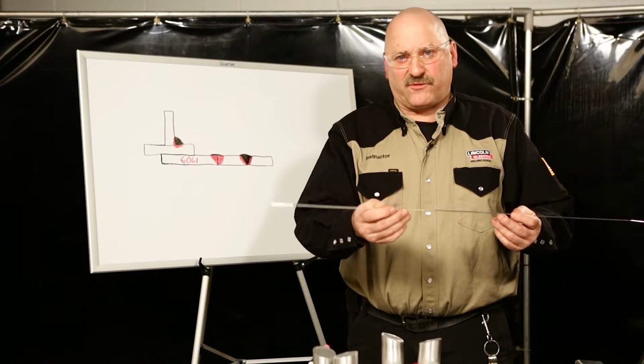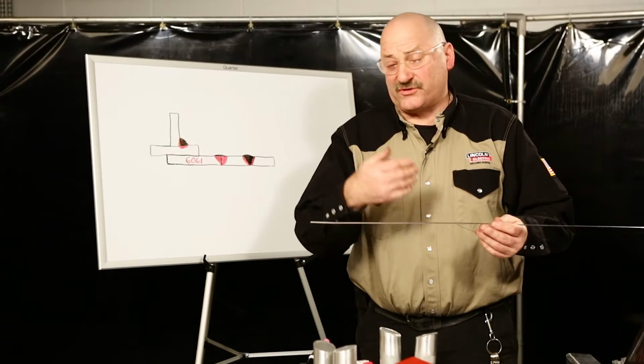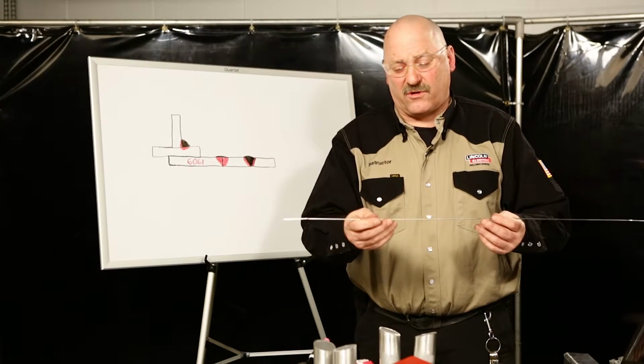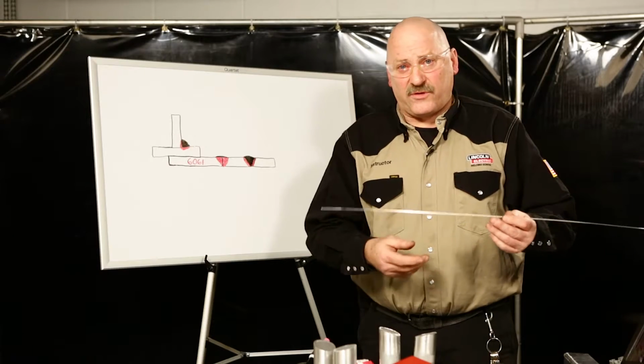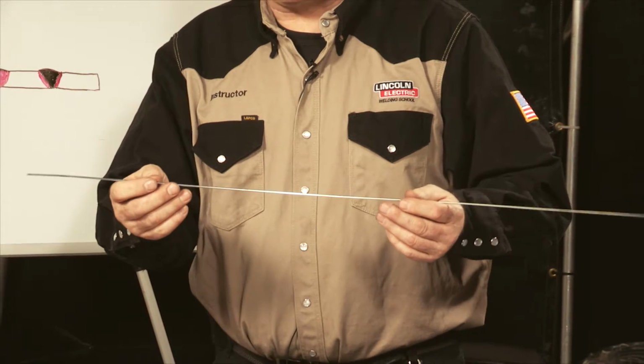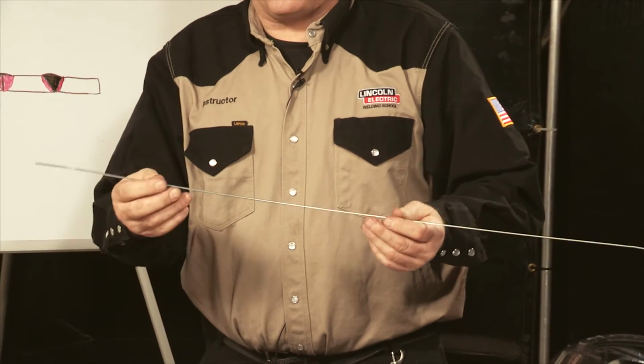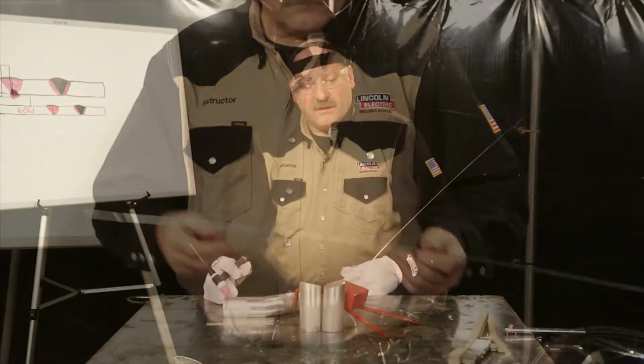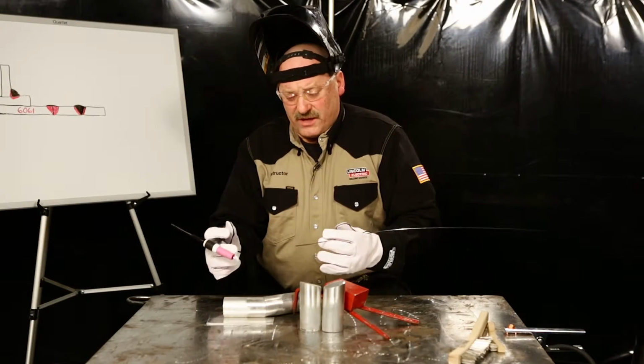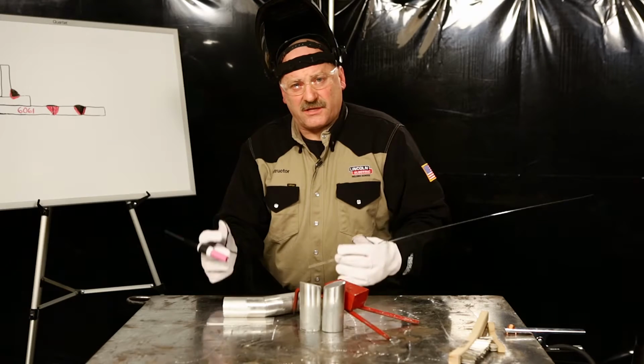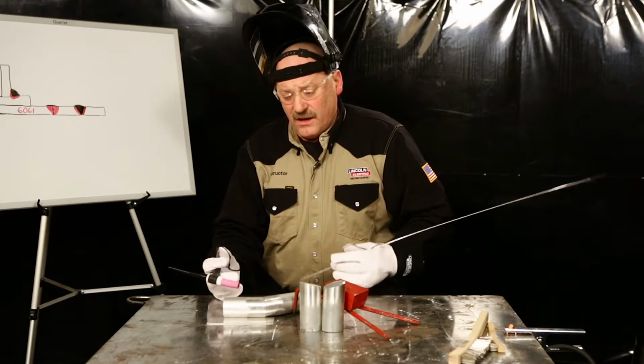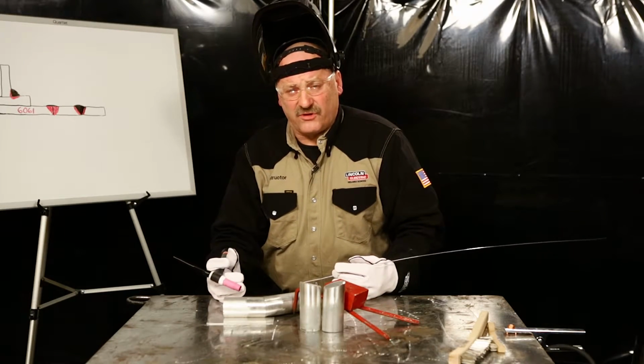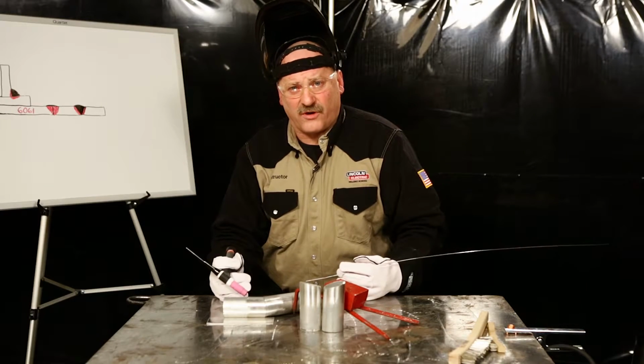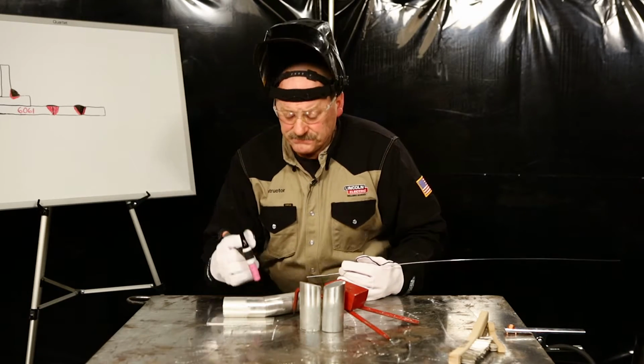There's a couple of different 4 series filler metals that would work. Also, there's some 5 series filler metals that would work as well. I'll be using a 3/32 diameter filler wire. 3/32 or 1/8 would both work quite well for this. The first fit up is going to be a square groove weld, fit tight together, and I'm going to try and penetrate in. I'm going to get very little filler metal in this weld, and this is the one that's going to be prone to cracking, so we'll see how it does.